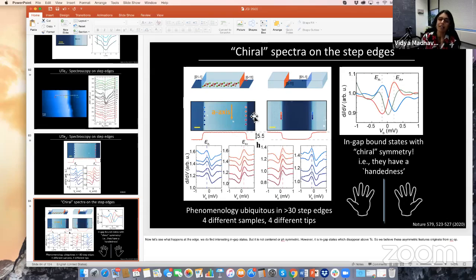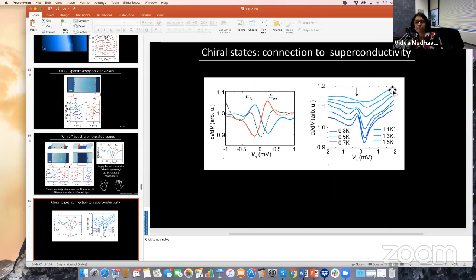So this peak is about 200 microvolts, and a dip on the opposite side, also at 200 microvolts. But the interesting thing is, if you go to the other step edge, then it's flipped. We checked this on many, many step edges, and what we found is that whether this peak is on the left or the right really depends on whether the normal to the step edge is pointing in this direction or this direction. So this system has a handedness, and so these in-gap states have a chiral symmetry.